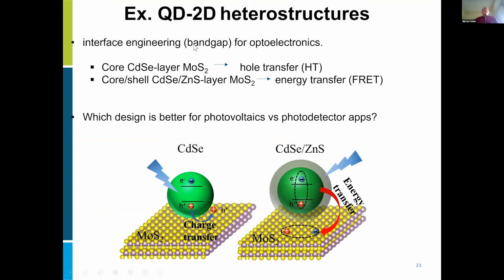In doing the interface engineering here for various optoelectronic applications, we were very interested to see how we can promote either charge transfer or energy transfer between this type of low dimensional semiconductors. And not only that, but which of the two designs is better for a given application: if it's the hole transfer functioning or the energy transfer functioning of the two designs. And we opted for stacking the quantum dots, basically.